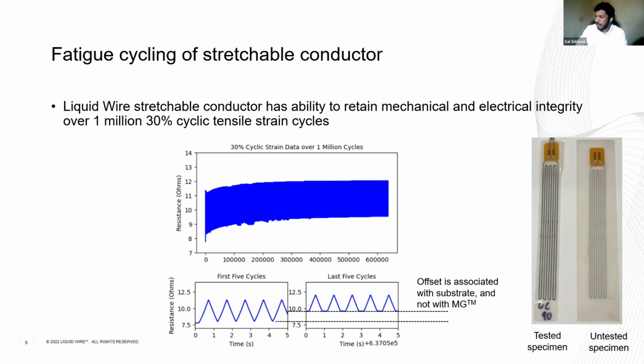When you compare the specimen before and after the test, you can see that the shift in base resistance is because the material did not have enough time to regain its shape, because we were stretching it at really high speeds. But if you do 1 million cycles at really slow rates, allowing the substrate to relax, you can see that metal gel can give a really good hysteresis-free response in a strain gauge.